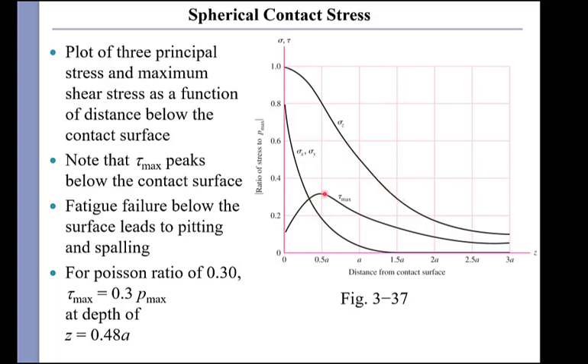The stress in the z direction is highest at the surface, decreases as we move into the contact. But if we look at Mohr's circle, that generates a maximum shear stress at a distance below the surface. It turns out that if the Poisson's ratio is 0.3, the maximum shear stress is 0.3 times the maximum contact pressure. And it occurs at a depth almost equal to half the contact.